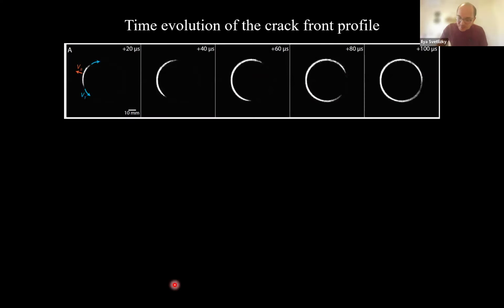Okay, so up till now, we ignored any transverse dynamics. So I assumed in the simple model that the crack expands like a circle. So it's a penny-shaped crack. And so let me switch gears and now try to explain the transverse dynamics. So we subtract the first image, focus on a single event, on a single jump. So the rupture nucleates at the top left corner. It starts propagating clockwise and anti-clockwise, and at about 100 microseconds, it completes the whole circle.